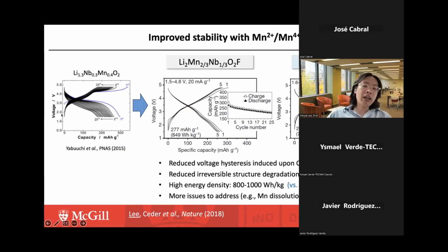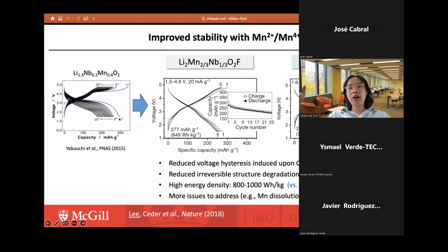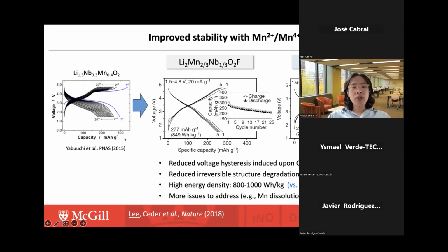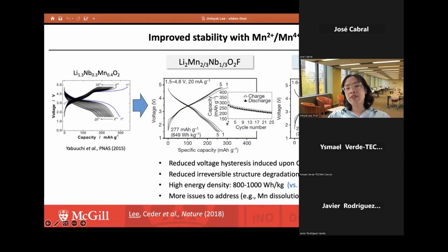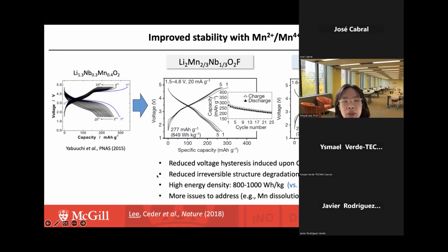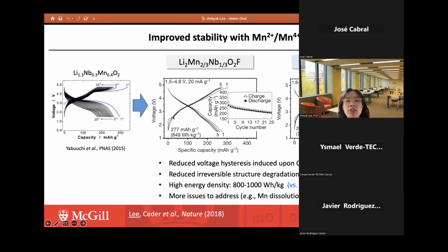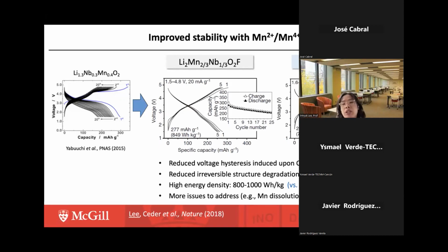For example, on the left side, I'm showing you the typical voltage curve of this lithium-excess manganese disordered oxide material, where you see the large voltage hysteresis and fast capacity loss. But if you look at the voltage curves on the right side and the middle, we see that the voltage hysteresis, which comes from the oxygen oxidation, is significantly reduced. So the voltage hysteresis is largely removed, and the capacity retention also becomes much better. And using XRD we found that the irreversible structure degradation is substantially suppressed.